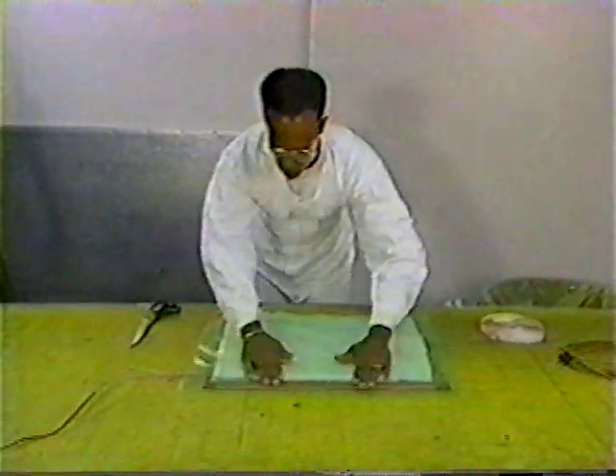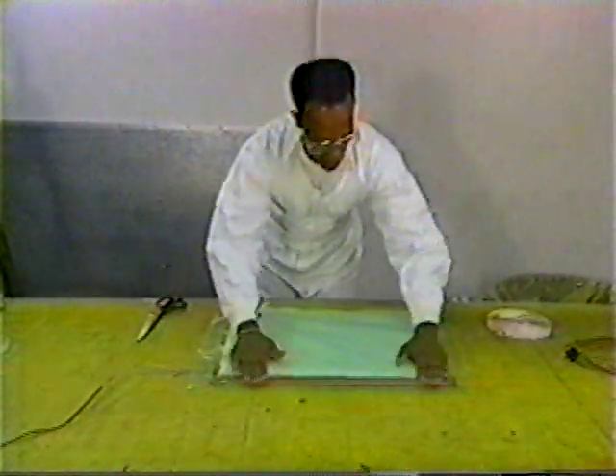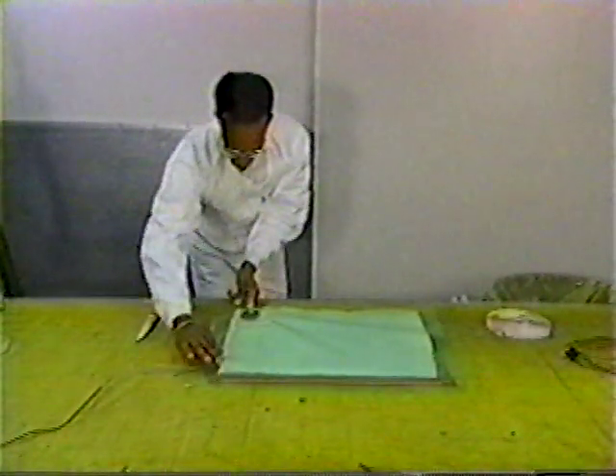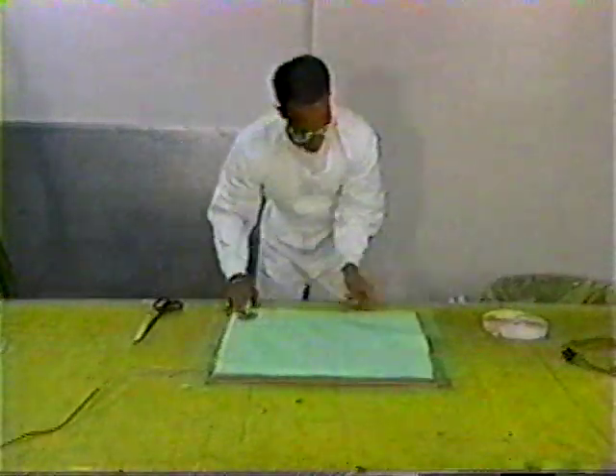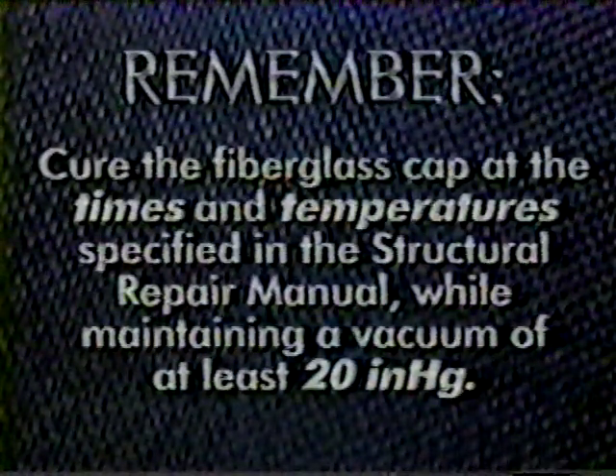Then, place a sheet of nylon bagging film over the stack of material and seal the perimeter edges with sealant tape. Cure the fiberglass cap at the times and temperatures specified in the structural repair manual, while maintaining a vacuum of at least 20 inches of mercury.